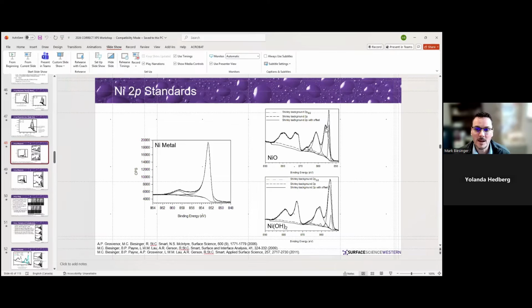The amount of times that we've been able to pull out nickel 3 and only seeing it through very, very controlled experiments, where we're trying to see in situ thin film growth on nickel metal, the growth mechanism that is postulated to have some nickel 3 production first before the nickel 2 proceeds or something like that. It's been a while since I thought about that. But being able to pull out that nickel 3 amount in that oxidation process, and usually only a small amount, it's not something we see a lot of.